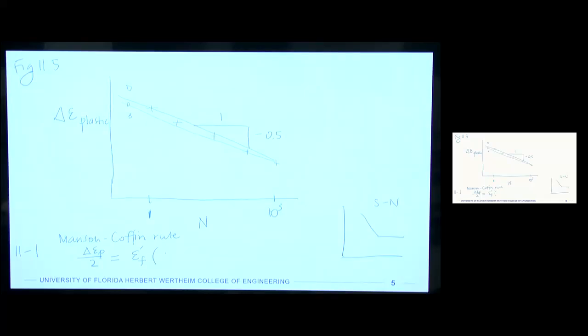And we're going to have a factor of 2 inside here. With the stress life approach, we didn't have that factor of 2, but we will have it here because each cycle becomes a little bit more important now. Before we had 10,000, 100,000, whatever number of cycles. Now we have 1,000 or 500 or 200. And so these 2's can sometimes make a difference. And then we would take that quantity to some power c, where c originally was like minus 0.5. This epsilon prime f at the beginning is what they call a fatigue ductility coefficient.